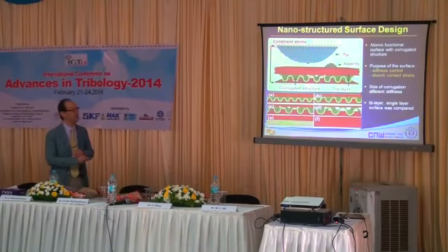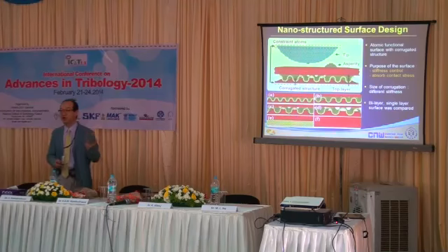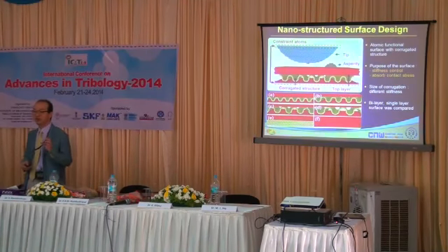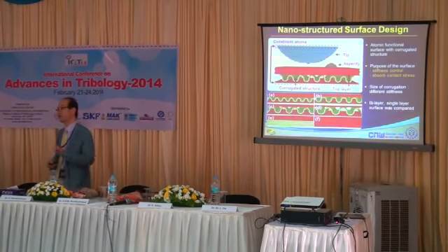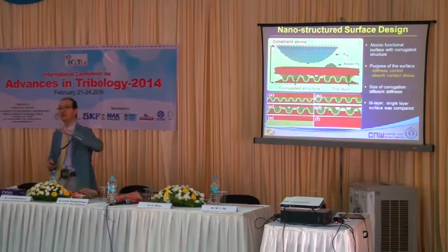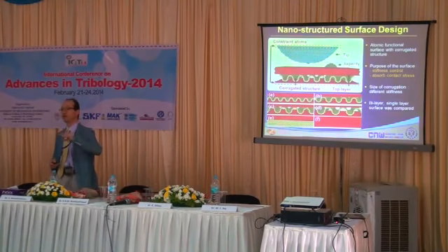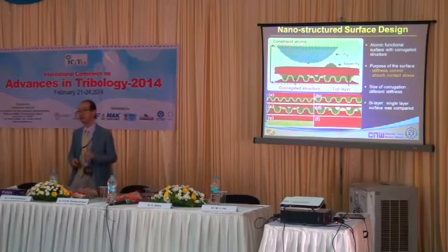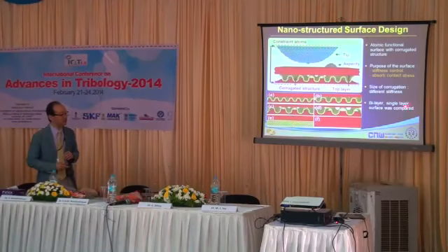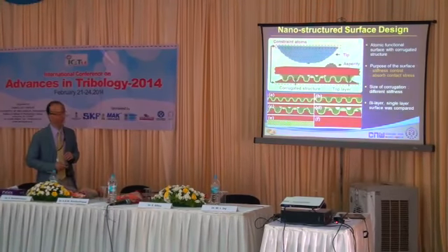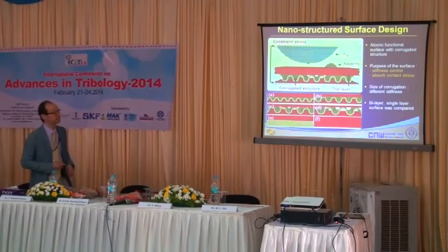Now, why is this asperity there? The asperity is there because in real situations, you will never have a perfect surface without an asperity. Asperity is always there, and we have to overcome interaction against the asperities to control friction and wear. So we tried that with different size corrugation, and also with a single layer and also a bilayer. So we use bilayer and single layer surfaces as well and compare that with these structured surfaces.